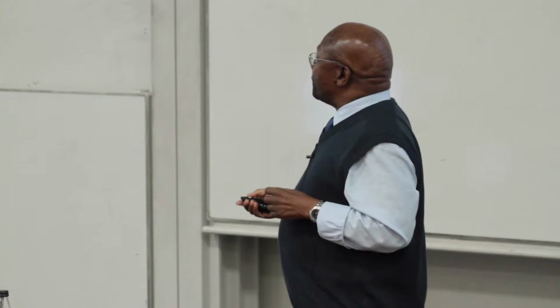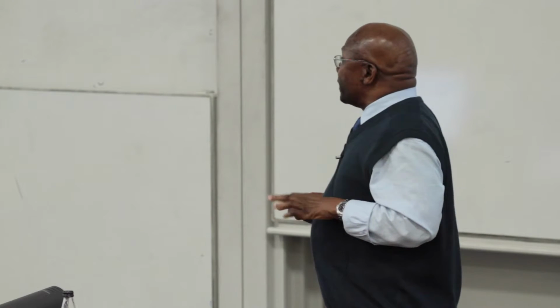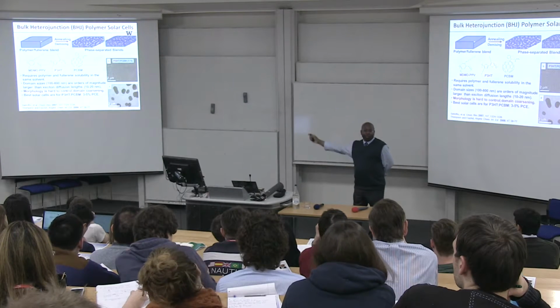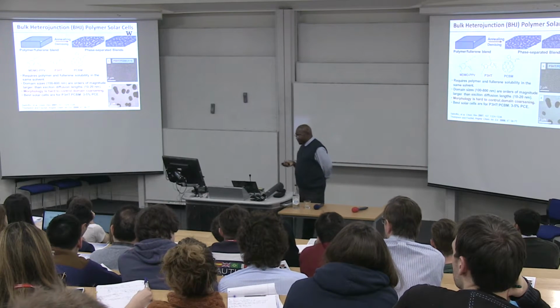And even if you have a very nice nanophase separated structure initially, what happens over time? Will you have domain coarsening? And indeed, that can happen, as demonstrated here, that the original morphology shown here becomes this over time, which is not good, right? Especially for devices that you hope that one day you'll be able to put on a roof for many years. All right, so at the heart, one of the big challenges in the field is really how to control the morphology of the bulk heterojunction active layer in these devices.